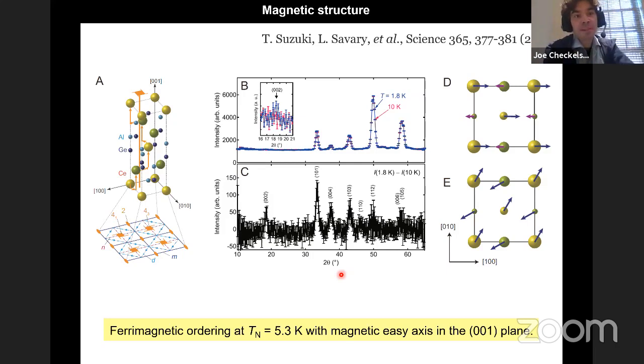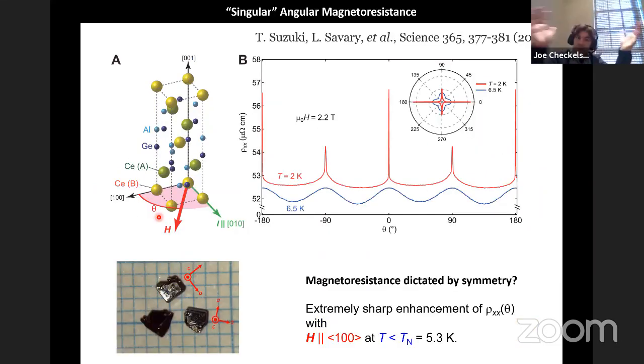to do neutron scattering. And what I will say just in brief is, by doing this elastic neutron scattering, we could really show what was the most likely magnetic structure in this antiferromagnetic phase for this particular material, this kind of ferrimagnetic order, and it could be characterized by all of the symmetries shown here. So why were we interested?